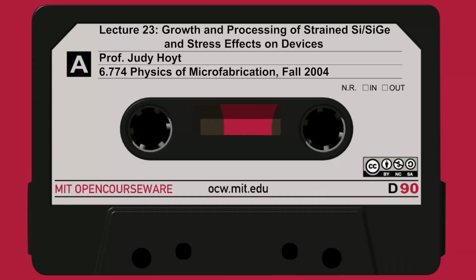So how do people do conventional scaling to increase ID, or speed, for logic? They make the gate length shorter. They reduce the gate oxide thickness. The real question in the last 5 or 10 years has been, what about the mobility? Is that a variable that we can tweak? We're pretty much done with scaling the gate oxide thickness. We can't get much thinner, only a few atoms thick. Making the transistor shorter is getting harder and harder, lithographically and for electrostatic reasons. We don't have too many more variables in this equation. So mobility is the last thing to touch.